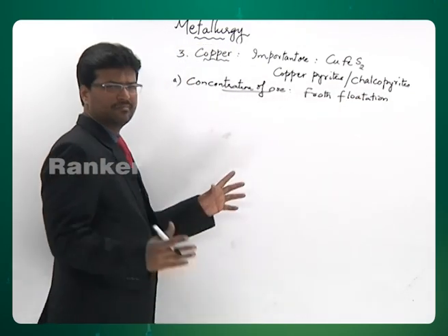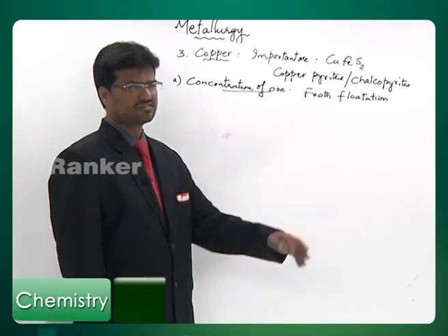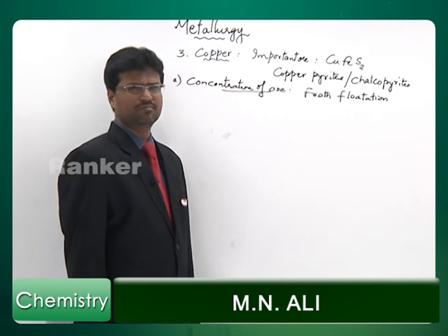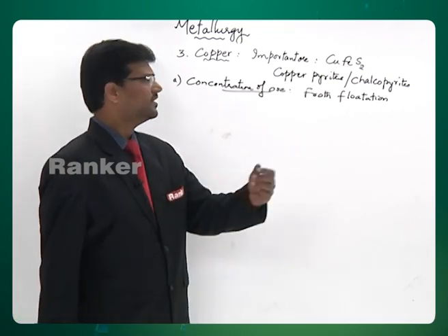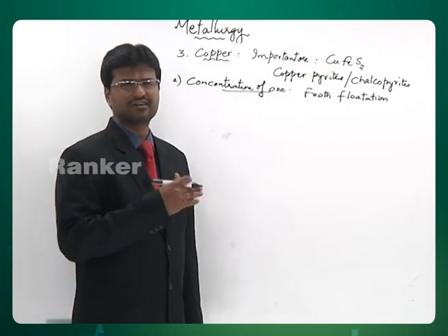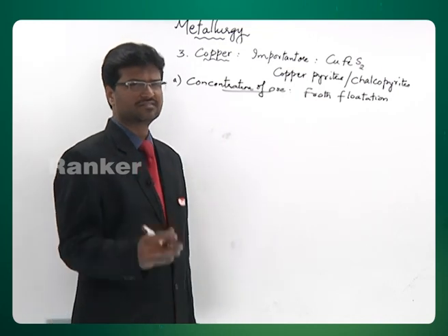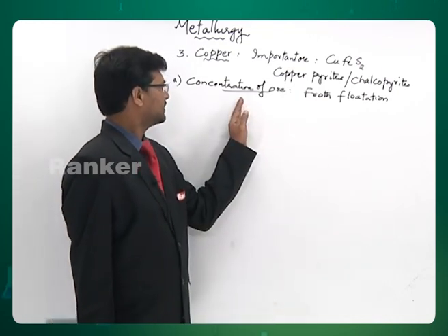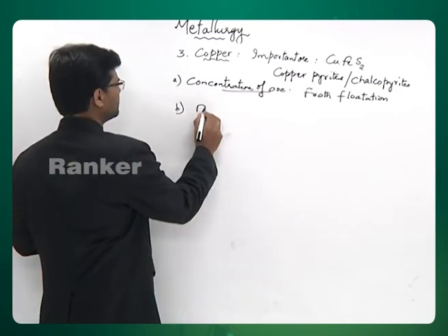In froth flotation, we put powdered ore in a tank, add lots of water, add pine oil, and then blow air and agitate the mixture. The ore particles stick to the froth, which is recovered and allowed to collapse, and then the oil separates out and the ore particles are recovered. This is concentration by froth flotation technique.